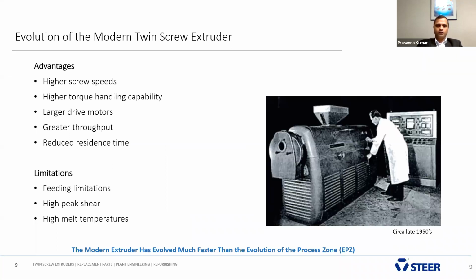Just to give a brief about the evolution of the modern twin screw extruder, as you can see in the picture, the first twin screw extruder, which was developed in 1949, had very low torque and low RPM. Since then the modern twin screw has developed in terms of higher screw speed, higher torque handling capability, larger drive motors, greater throughput, and reduced residence time. So there has been a very drastic improvement in the extruder specification itself, but we do find limitation in the extruder processing zone. When I say extruder processing zone, that's where the material is being transformed to the desired product.